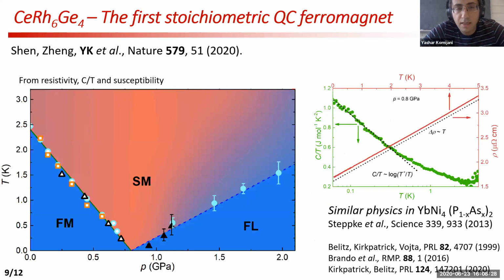All right. So recently, in this work, they have studied this material, and from the resistivity, specific heat, and susceptibility, they could extract a phase diagram shown here as a function of pressure, and this is the temperature. So we have two phases: a ferromagnetic phase and a Fermi liquid phase, and the energy scale associated with these two phases collapse at the critical pressure.